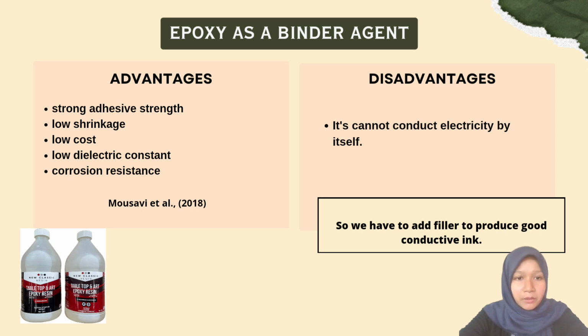Next, we use epoxy as a binder agent in the conductive ink. The advantages of epoxy are strong adhesive strength, low shrinkage, low cost, low dielectric constant, and corrosion resistant. And the disadvantage is it cannot conduct electricity by itself, so we have to add filler to produce good conductive ink.